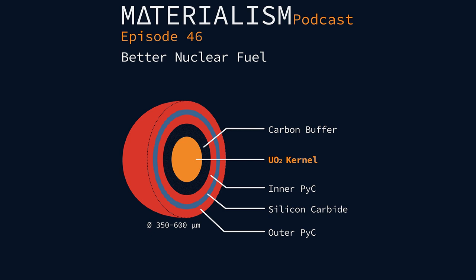The U.S., on the other hand, continued to pursue their uranium oxycarbide designs, with both fissile and fertile particles being present. They kept running into issues where particles were failing, and so they then designed the TRISO-P particle, which added just an additional pyrocarbon layer, thinking that that would help prevent it. But these were less satisfactory than the Germans' uranium oxide fuel, and they still had tons of issues. Most of the U.S.'s TRISO development was halted in 1993.